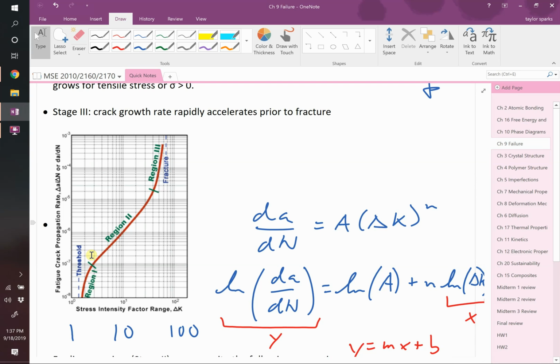Let's say that we call up QTI and they tell us that a flaw is such and such a size. We could then do the math if we had the constants, and we could say, okay, it's going to be another 500,000 cycles before this thing fractures. So we can either use it or we can't. Maybe need to replace it. They do this all the time. On airplanes, they literally take ultrasound measurements of the hulls of airplanes, and there are cracks in every plane that you fly in. They're just not critical yet, and they can monitor roughly the rate at which they grow, so they fly it until it's not safe within some tolerance factor, then they swap it. Nobody looks horrified by this. It's semi-horrifying, right?